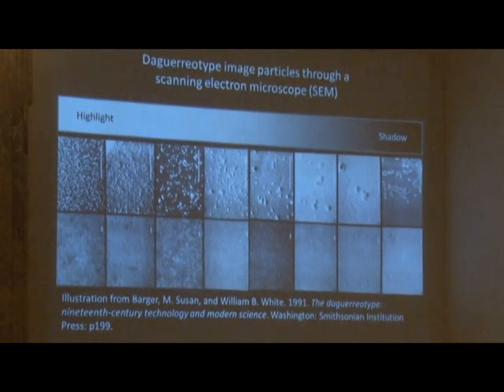The images on the top are the same area as the bottom, but at higher magnification. The high magnification images help you see the shapes of the image particles, whereas the low magnification images help you see the distribution of the particles. In the highlight, the image particles are very small and regularly sized, and they're nice round shaped. It's a little hard to see, but they're really consistent. And they're close to one another and evenly distributed.